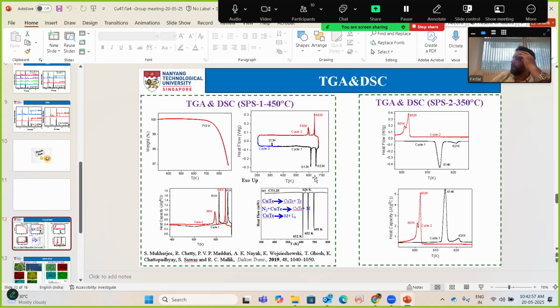Okay, so you'll find out. The other way to do this is you pre-mix the powders, and this is what Haiwan has been doing. You can take the same powder, and he has temperature control for his synthesis with the carbothermal shock. We've done it in non-contact. So we're not looking at densification, we're just looking at phase formation. And it should complement your NCD-XRD, right? Haiwan, you know how to do this.